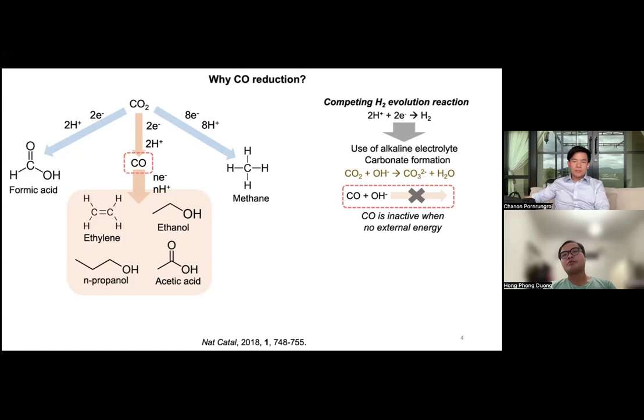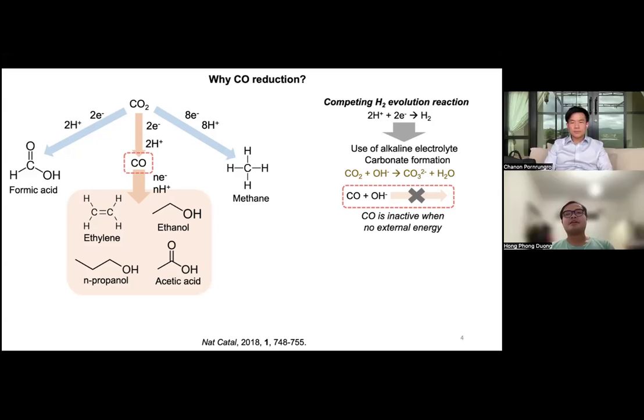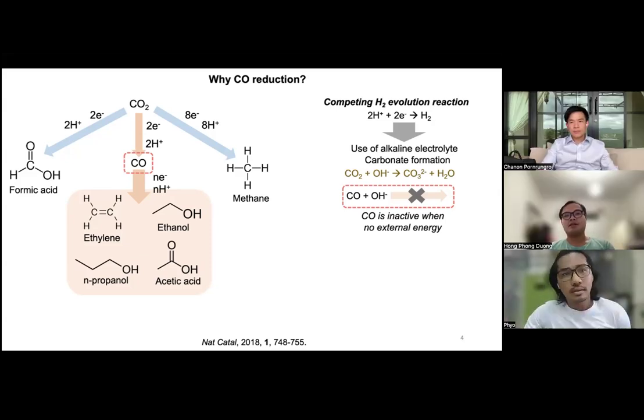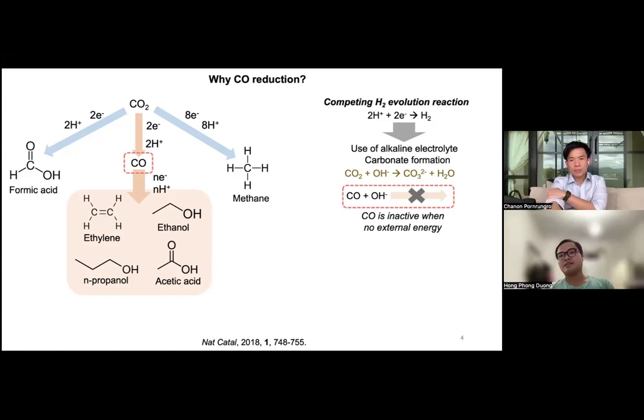Why? Because we would like to minimize the hydrogen evolution reaction, which is a competing reaction with the CO2 reduction. Of course, getting hydrogen from electrolysis is very nice as well, but in this case, we care more about the CO2. We don't want the hydrogen. So this is why we usually work with very high pH to avoid these unwanted reactions.